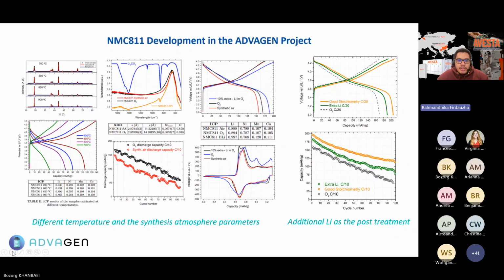Here we can see that the discharge capacity with synthetic air and with oxygen shows a difference. So we have a short conclusion: with oxygen we can have a good result in the capacity and also other performance. In between, we also need to maintain the lithium, because the oxygen affects the lithium content, so we need more excess lithium during the development. So we add 10% extra lithium in oxygen atmosphere, so we can get the desired capacity that we want to go further. Even in the electrochemical performance, we can see a huge difference between oxygen and synthetic air.